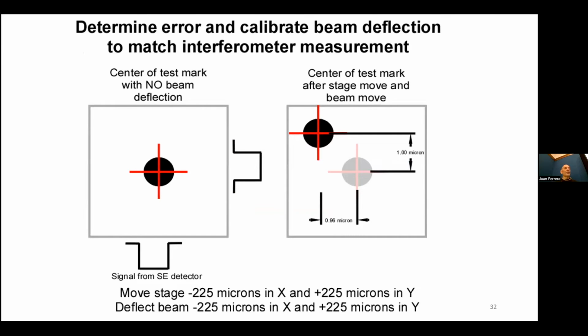So how do we get the deflection to be so precise? Because we want this deflection to be good to at least 1 part in 10,000. And the answer is we close the loop with the laser interferometer. The way that's done is we put a mark here in the middle with no beam deflection whatsoever. We scan across it in X and Y, and then we find the center position of each thing. So we find the center position in Y, center position in X, from our secondary electron detector.